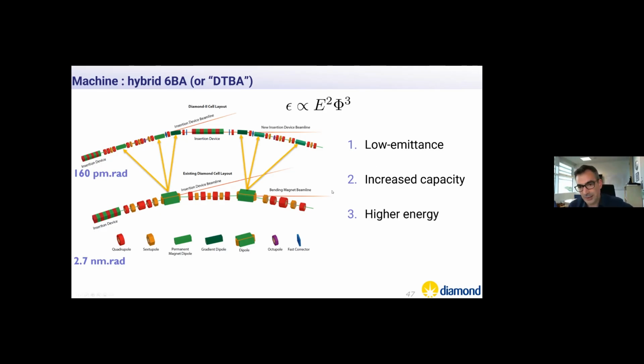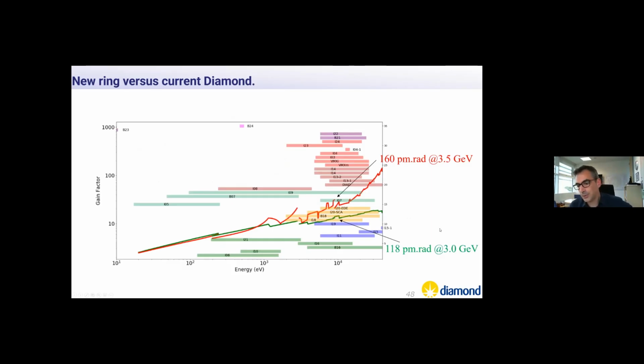At the same time, it appears a little bit counterintuitive, but the emittance goes quadratically with the energy of the ring. So in principle, the last thing you want to do is to increase the energy of the electrons in the storage ring. But actually, instead of pushing the emittance down to 120 picometers, which could be possible if you kept the current synchrotron at 3 GeV, if you increase the energy to 3.5 GeV, the emittance increases, so it's not as good, but you also increase the flux at the same time.